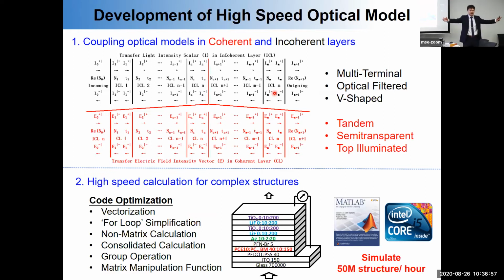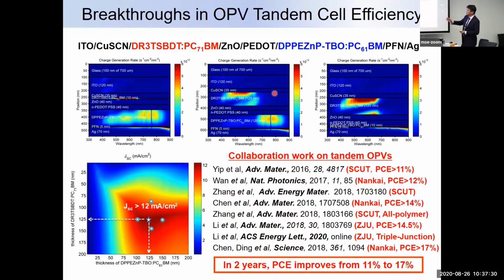Now, for example, if you have two devices separated over 1 meter, we can still calculate the light propagation for these two devices. We are also trying to increase the calculation speed by a lot of modification of the code. So now, just using a laptop, we can calculate about 50 million structures per hour. So this is increased by close to 10,000 times compared to the commercial model. So this is one example.